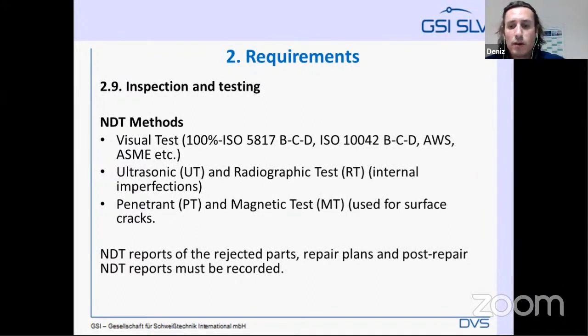NDT methods. Visual test. The most important NDT method is the visual test, because visual test must be performed 100% for each part, and acceptance criteria, for example, ISO 5817 or ISO 10042, and acceptance levels B, C, or D must be given. Also, the other test methods and percentages must be determined according to the execution standard or customer specification. They are ultrasonic test or radiographic test, UT or RT, for internal imperfections, and PT and MT, which are used for surface cracks. NDT reports of rejected parts, repair plans, and post-repair NDT reports must be recorded in the quality file.